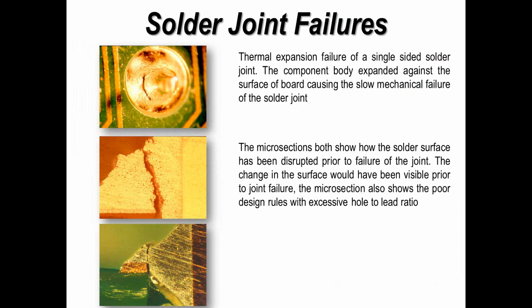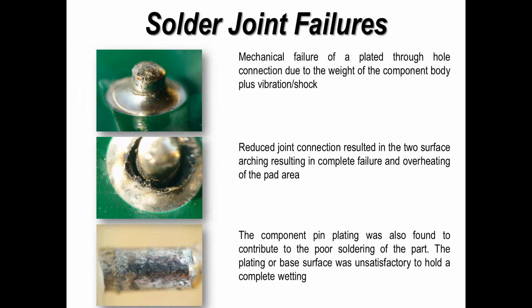These 3 examples are thermal expansion failures. And basically what we've got here is a single-sided board, and the solder joint is formed, but either the pin was expanding and contracting against the laminate surface and literally pulling it out of the solder volume. So if you've got the wrong hole to lead ratio, this will happen quicker. If you've got the right hole to lead ratio for the same design, it will take longer. If you add more solder to the joint, it will last longer, but inevitably it will still fail at some point.